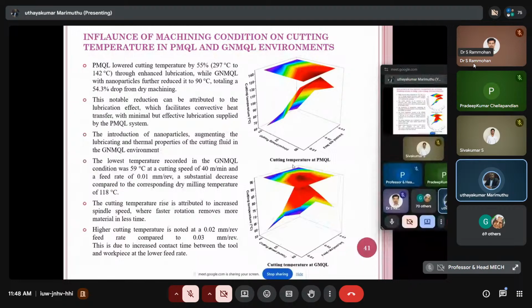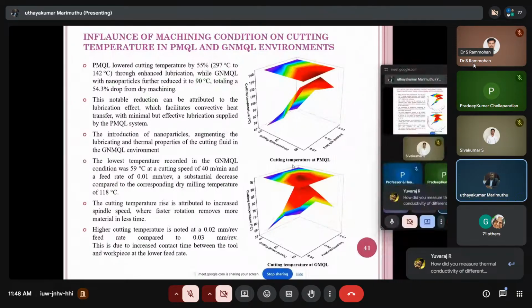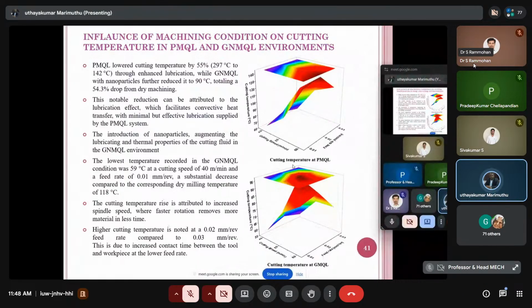While in GNMQL, the nanoparticles further cooled it to 90 degrees centigrade, a 54.3% drop compared with the dry machining process. This notable reduction can be attributed to the lubrication effect, which facilitates convective heat transfer with the minimal but effective lubrication supplied in the PMQL system. The introduction of nanoparticles augments the lubrication and the thermal properties of the cutting fluid in the GNMQL environment. The lowest temperature recorded in the GNMQL conditions was 59 degrees centigrade at a cutting speed of 40 meters per minute and a feed rate of 0.01 mm per revolution.